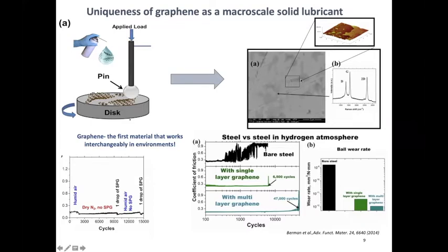There are some places where it's darker and some where it's lighter. So in some cases you have single layer graphene and in some double layer, triple layer. They also demonstrate a pretty high D peak, which tells us that we have some level of oxidation happening on the edges of the graphene flakes. And even with all these disadvantages, the imperfection of our graphene coating, it's providing very stable, low friction, low wear behavior. We also tried to see how we can further improve this behavior, and found that if we do the sliding in a hydrogen atmosphere, we can extend this behavior even further, because we are actually using hydrogen for repairing our systems and providing more uniform sliding.